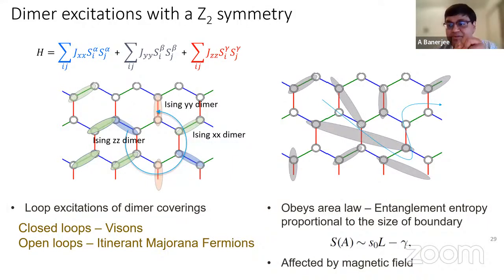you can get to a spin liquid state, but that classical spin liquid does not give you the gap at the gamma point. There is no two flux gap. So basically what you get is just a simple continuum which is peaked at zero energy, and more or less the zero energy spectrum looks like a paramagnet, and then you basically get another mode which hangs right at the Ising point, and that's more like a bosonic mode, which is much sharper. It doesn't look like this broad energy continuum, this fermionic-like continuum that we see.